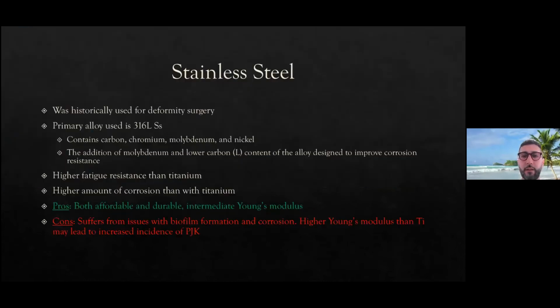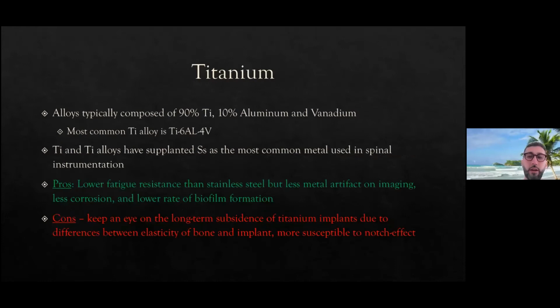So, kind of to summarize this and put this together in terms of understanding these various metals, stainless steel, as Dr. Levy mentioned, isn't really used much anymore. Was historically used a lot for deformity surgery, and this is what it's composed of. It has a higher fatigue resistance than titanium, but it also has a higher amount of corrosion than titanium. So the pros are it's actually affordable and durable and has an intermediate Young's modulus, but it suffers from issues of biofilm formation and corrosion. Higher Young's modulus than titanium can lead to increased incidence of PJK and actually more imaging artifact.